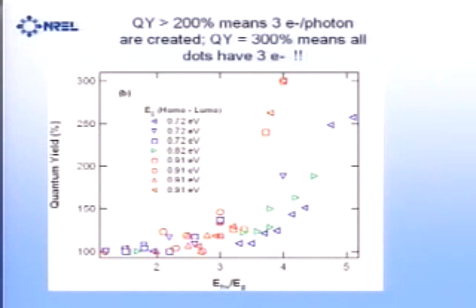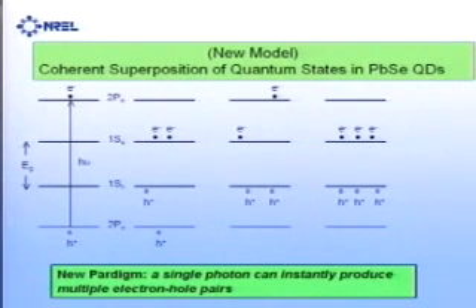And you see for the smallest band gap at around 3 times the HOMO-LUMO transition, which corresponds to about 2.7 eV, so it's still in the visible, we begin to get a very dramatic rise in the quantum yield. And when we're at 4 times the band gap, we're getting 3 electrons per photon. So this is quite remarkable, to get a quantum yield of 300%. Now, the other important thing, as I mentioned, is that the explanation for this is based on a new paradigm for this effect. It's not impact ionization. It's actually a quantum mechanical effect.